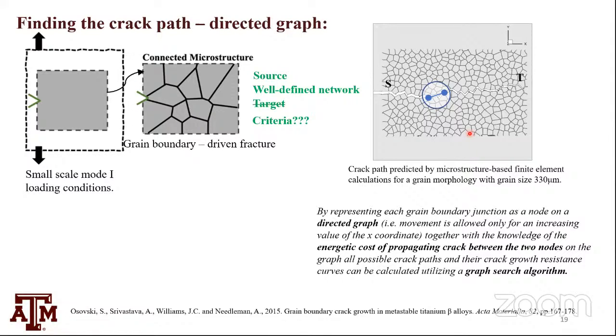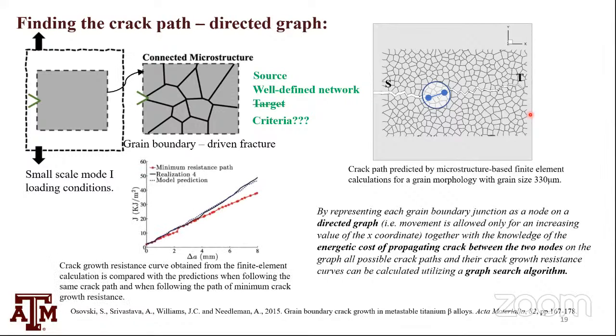Richard Feynman once said, if you give me all the possible paths between A and B, I can tell you the path of shortest, minimum energy. So let's draw from that. And since I know all the paths, I can find the path of least resistance between S and T. Now this is the crack growth. The black line is the crack growth resistance curve predicted from finite element. Red is the path of least resistance. It underpredicts the total crack growth resistance, and it underpredicts more and more as we keep going on. That means the crack does not follow the path of global least resistance.